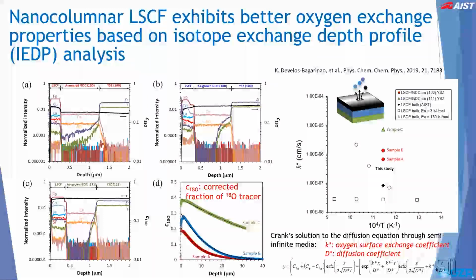To investigate this, we measured the amount of isotopic tracer that was incorporated into the samples as a way to evaluate the surface reactivity. These are typical SIMS depth profiles obtained for the three different samples. The plots shown as A, B, and C show the various elements comprising the different layers as a function of depth. The black line, in particular, refers to the 18O oxygen isotope, which you may recall was used as a tracer for the experiment. In the plot shown in D, we can see that the film having a dominant 110 orientation, shown in green, shows the highest concentration of 18O incorporated into the YSZ electrolyte.